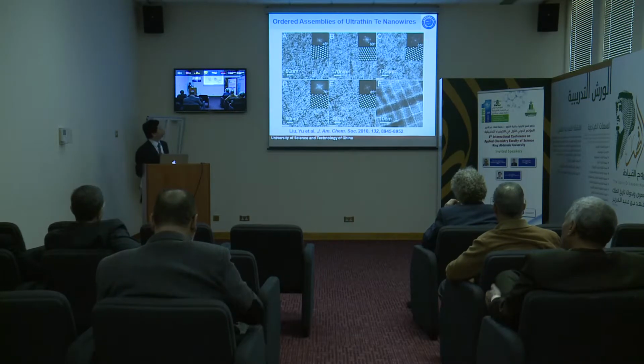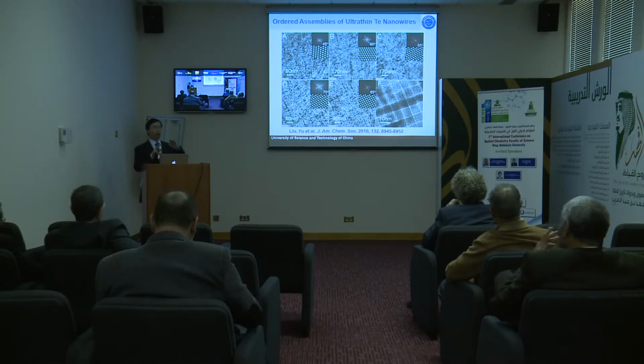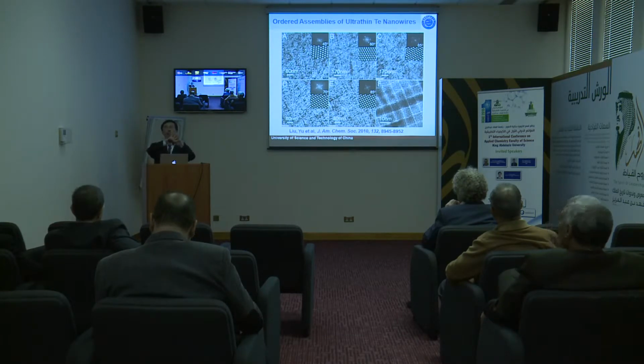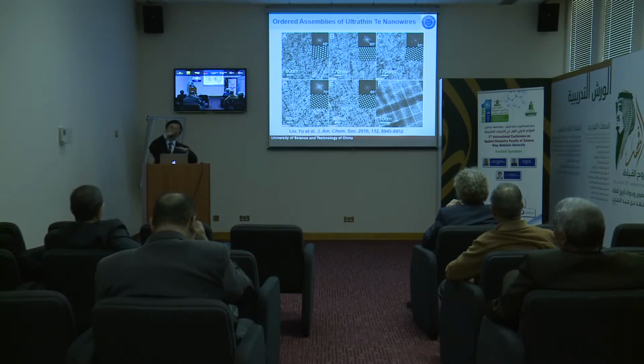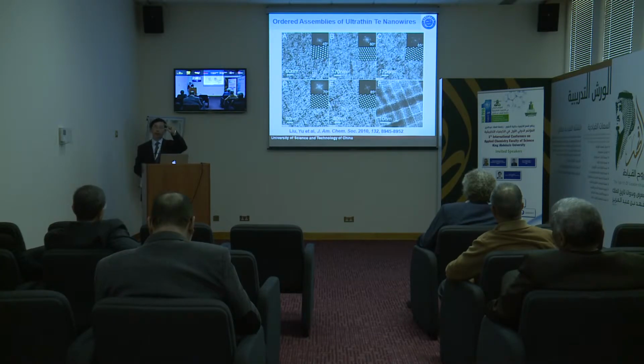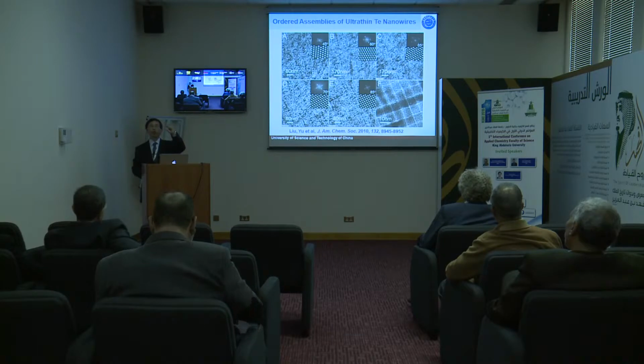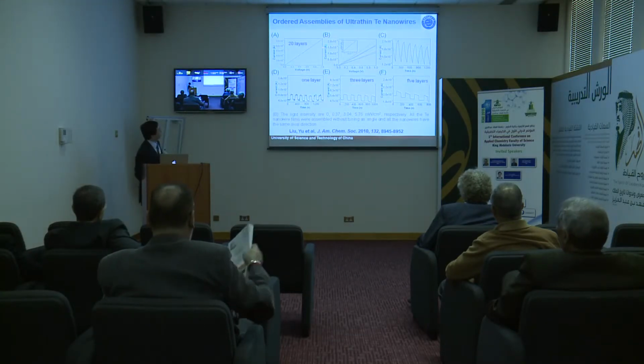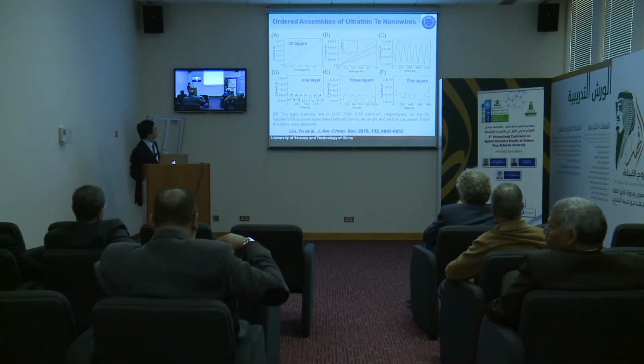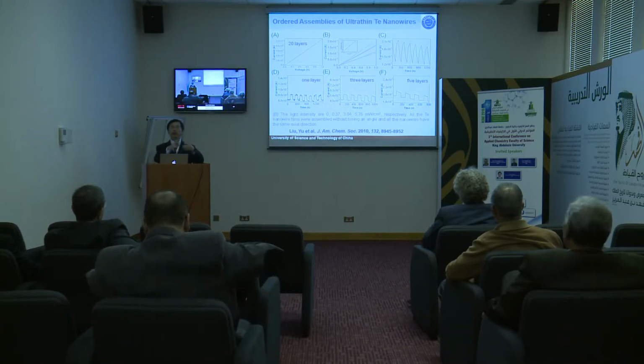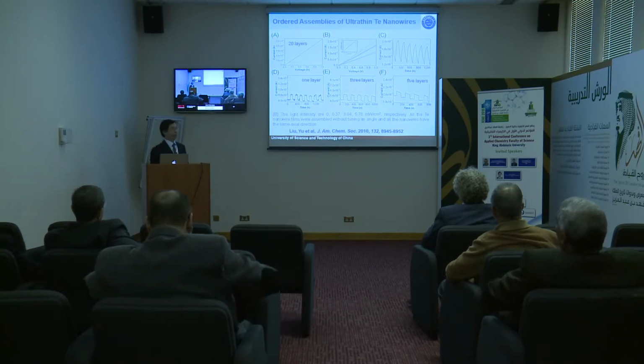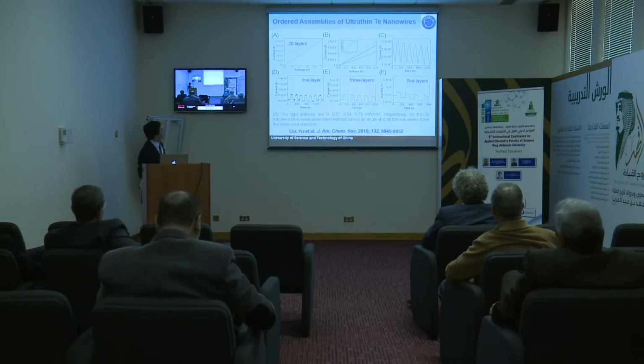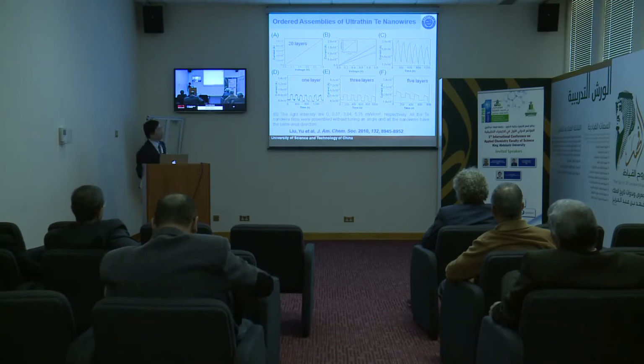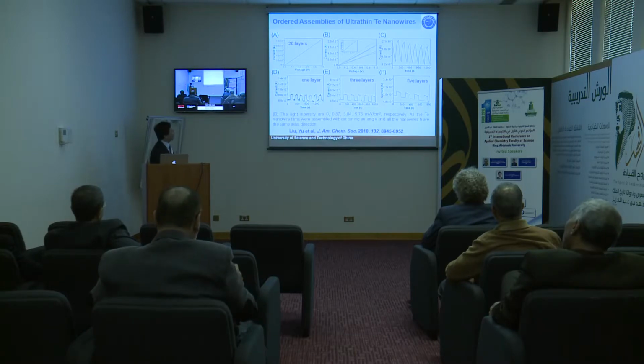Here is some data showing two layers with a different turning angle. You will get this mesh-like nanowire network. This is the two layers. But of course, you can do third, fourth, and more layers, so that you can get a nanowire thin film with tunable thickness. So we use them for photoconductivity applications. We can use this large-area nanowire thin film to construct a nanodevice for photoconductivity. You can identify the layer-number-dependent electron current generated by this assembled nanowire system.